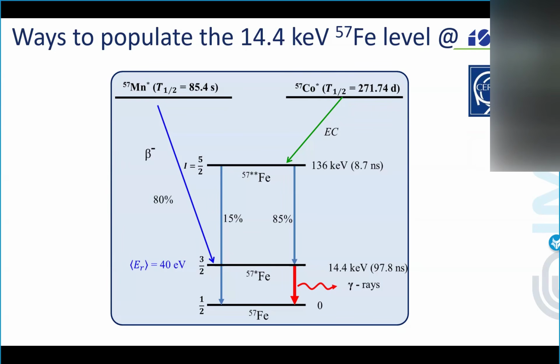And there is also another way, which is less common, but we used in the past, which is to implant cobalt-57, basically to build up a source in your sample. But of course, it's 10 to the 12. So we cannot make a source that then can be used in the lab. But you can produce the long-lived sample that you can bring home if you are allowed to handle radioactive samples. And in Leuven, they were very expert in doing that. And you can then use your sample as a source, even at home.